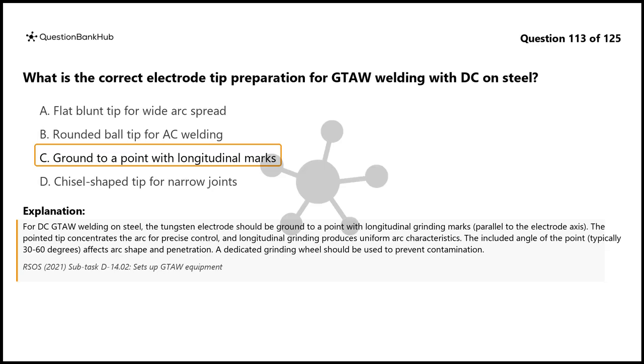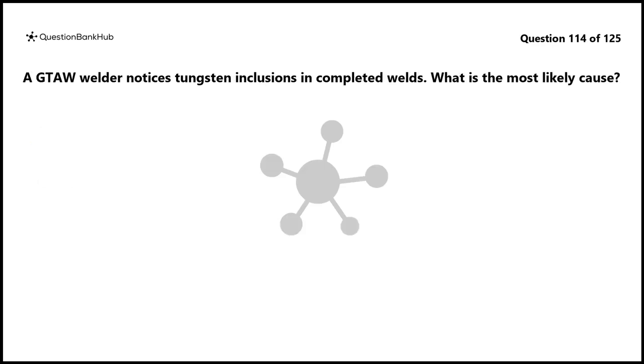The included angle of the point, typically 30 to 60 degrees, affects arc shape and penetration. A dedicated grinding wheel should be used to prevent contamination. Question 114. A GTAW welder notices tungsten inclusions in completed welds. What is the most likely cause?